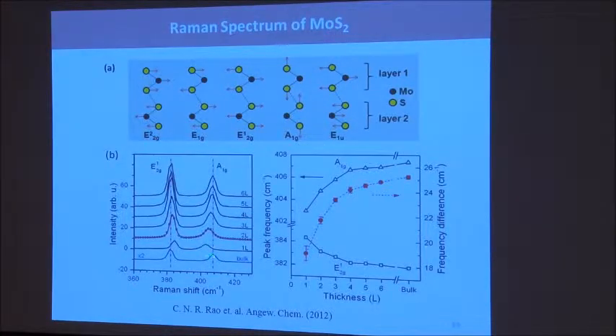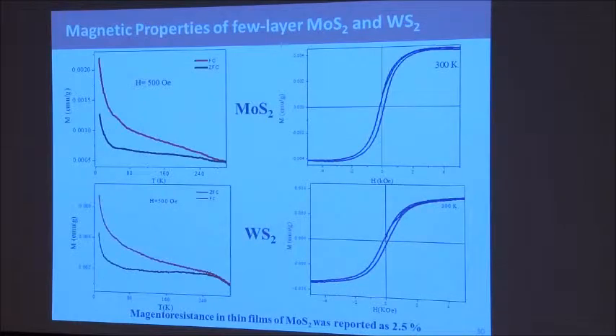If I make one layer, this band shifts to the left—that is, it softens—and the second band goes to the right, it stiffens. So the softening of the A1G mode and the stiffening of the E12G mode as you vary the number of layers, from bulk down to one layer, shows this softening and stiffening. This is very useful in characterizing single, two, or triple-layer molybdenum sulfide and materials of this kind, and it is also a very interesting spectroscopy by itself.